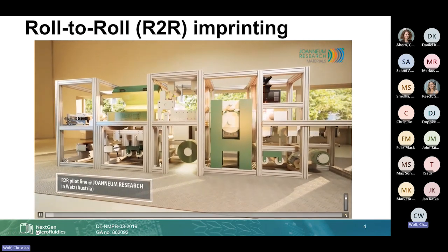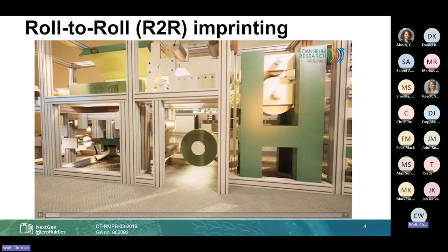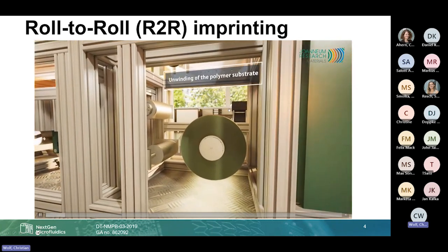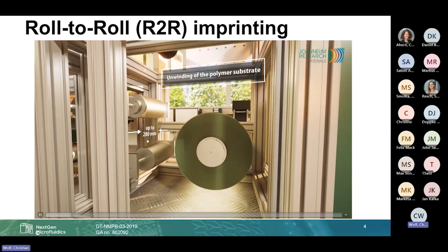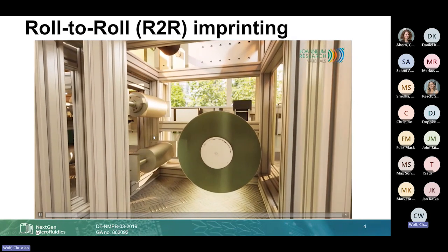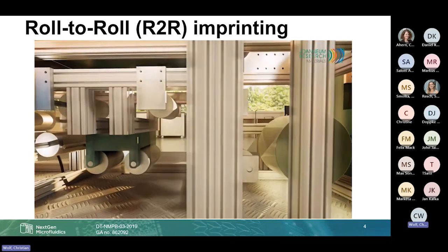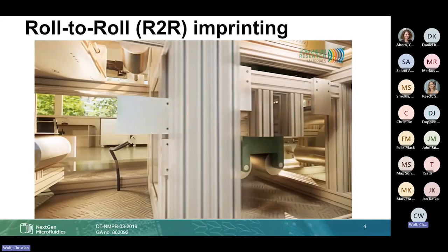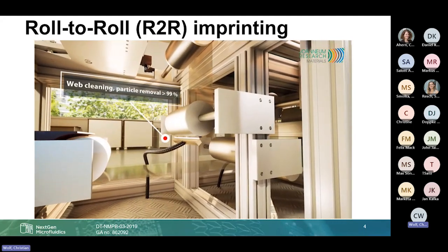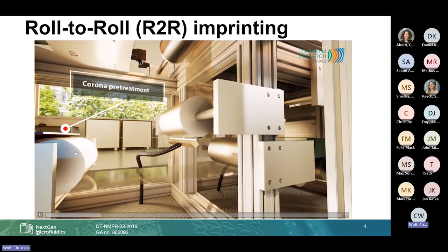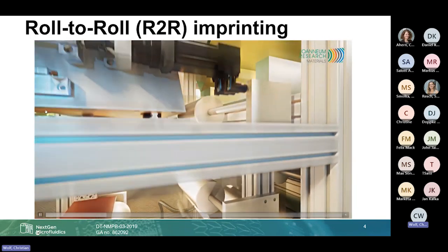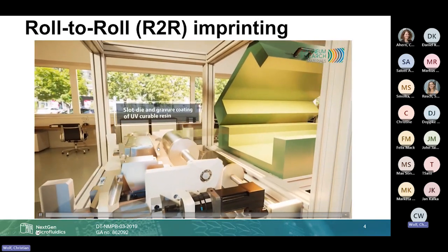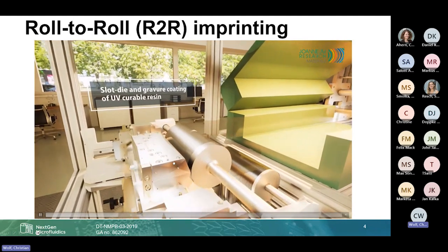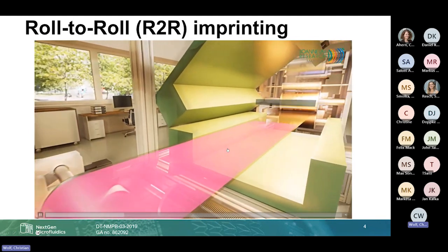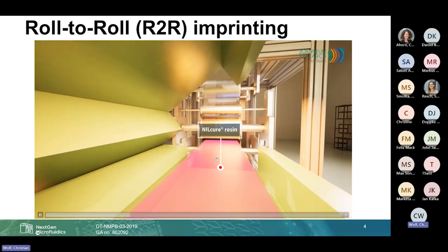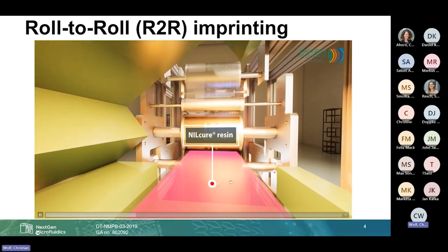Everything starts, surprisingly, with a big roll of a substrate foil, a carrier foil, in our case with a width of up to 280 millimeters. Material-wise, you're quite free, but the only important thing is that the foil is transparent. Why? We will learn later on. Then there's a cleaning step, and you can also do some corona pre-treatment, which can be important for the next step to improve wetting properties, because then this carrier foil is coated with a thin layer of a resin, an acrylic resin, which can be cured and hardened by UV light.